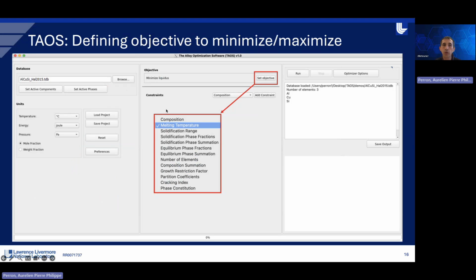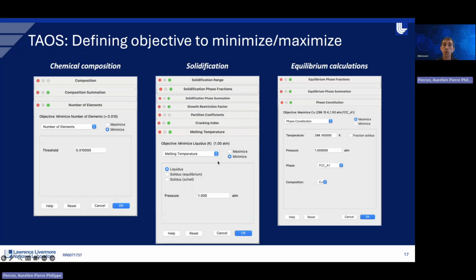So now let's go to the middle panel, where we set the objective. In that specific example, we are interested in minimizing the melting point of the alloy. But you can see that you have a lot of different options already included in the software. I won't go through all of them, but you can technically minimize or maximize any of these functions. You can be interested in chemical composition. So here, for instance, if you want to do high entropy alloys or something like this, you can use a target such as the number of elements, and try to maximize the number of elements in your alloy. Regarding solidification, again, there are a lot of different factors: solidification range, nucleation, cracking indices, or melting temperature, as in this example.